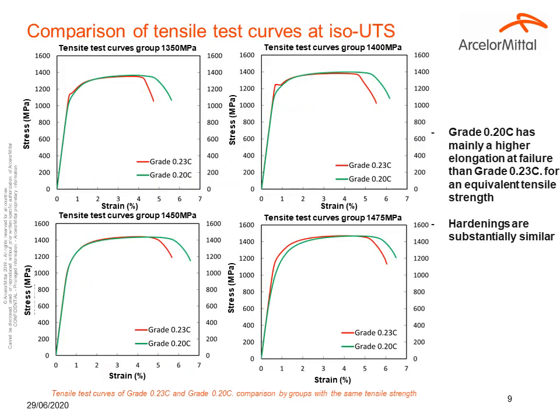Here is the comparison of tensile test curves for our four different groups with the same tensile strength. You can see on all these curves almost the same tensile strength for the two different steels in one group. In these four comparisons, the grade 0.20 has mainly a higher elongation at failure than grade 0.23 for an equivalent tensile strength. However, the hardenings are almost similar when we compare steels in one group.